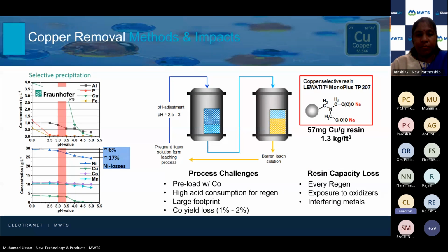And here's just, again, showing you a little more example of the yield loss from precipitation. This is some data pulled out from a German research institute, showing real data that nickel and cobalt will come out if you use chemical precipitation. But the ion exchange is just massive, right? The capacity for these copper selective resins is not big enough. So you end up having half of your plant is now ion exchange